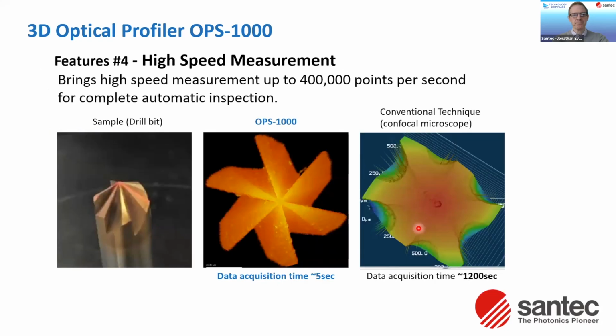High speed I mentioned, well, our lasers can scan up to 400 kilohertz, so 400,000 points per second can be measured. So how does that come into play? Well, again, going back to the drill bit, the OPS acquired that image in 5 seconds, whereas the conventional confocal microscope took 1200 seconds. So you're talking about, for the same resolution, the same area covered, seconds in terms of the image acquisition over minutes.